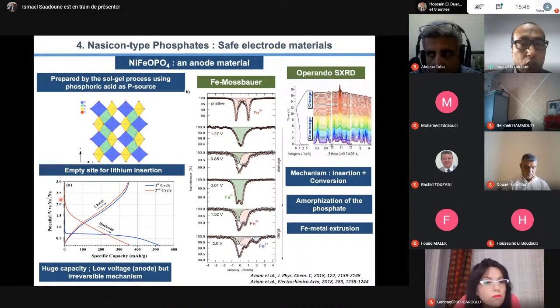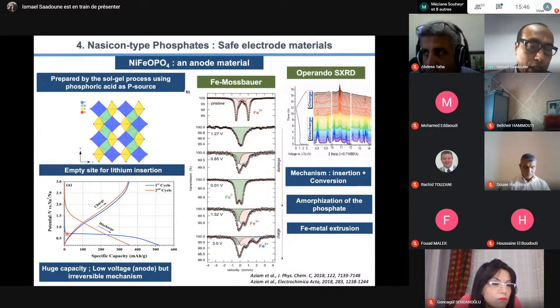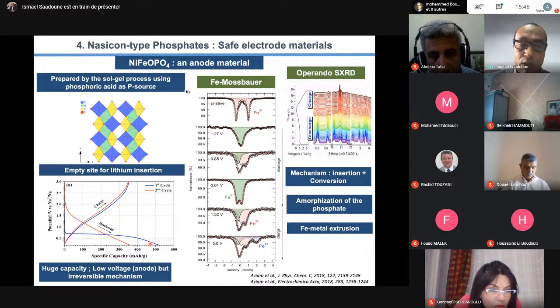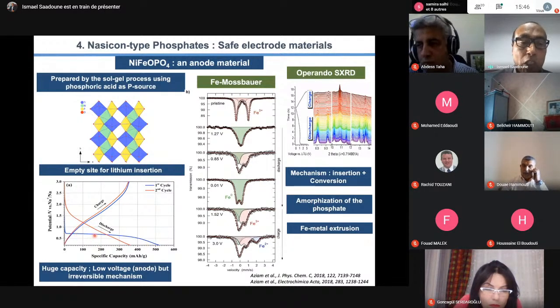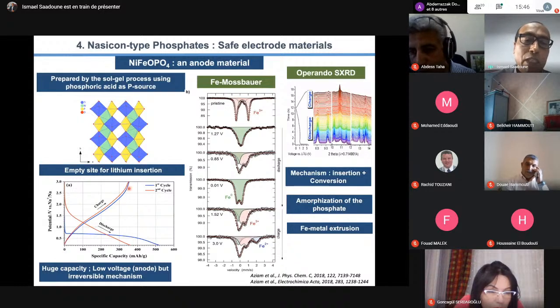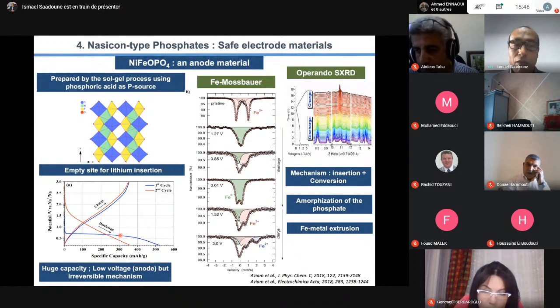This is the discharge in blue, the first discharge. You see, we have a good plateau at very low voltage, anodic voltage, and a huge capacity, better than the graphite used now commercially. But the problem is when we recharge the battery, we have a new profile - you see, we have some irreversibility. Normally we should have a curve like this, but we have this irreversibility, and we should understand why.